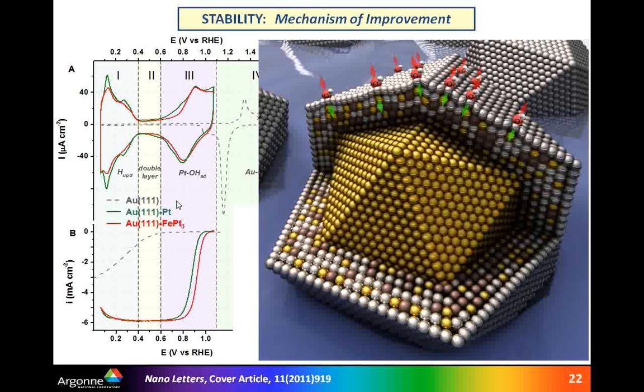So, in order to explain that, we used again our single crystals that were initially covered with pure platinum, with bimetallic film, and also we used gold to compare. And one can see in the background that cyclic voltammetry of gold and bimetallic systems is substantially different. And the onset of oxide formation on platinum and platinum bimetallic starts as low as at 0.6 volts, while at gold it starts at potentials that are higher than 1.2 volts.